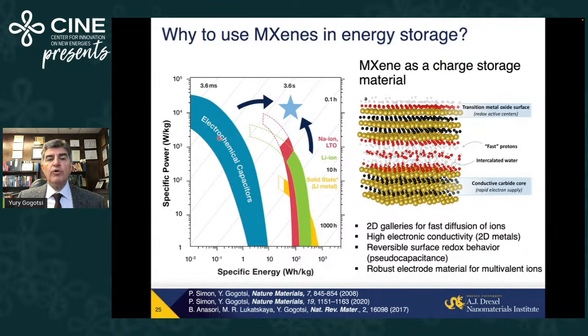Ti3C2 is about two orders of magnitude more conducting. Other MXenes will be at least the same conductivity, many will be an order of magnitude more conducting. So what it means is that we have all the properties in these materials needed to really achieve the goal of high energy, high power energy storage.